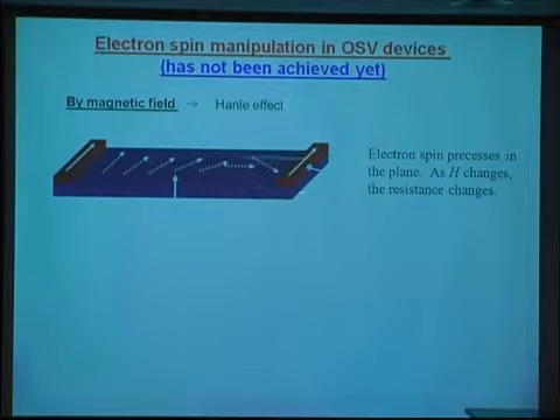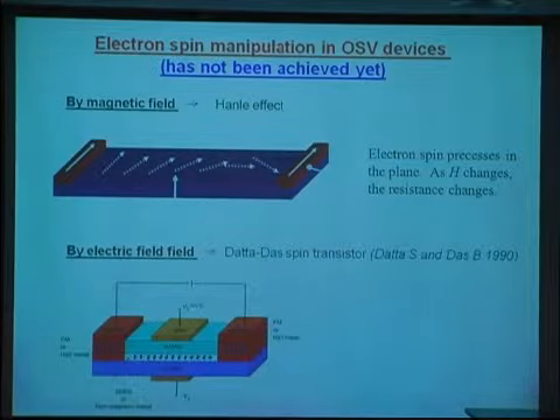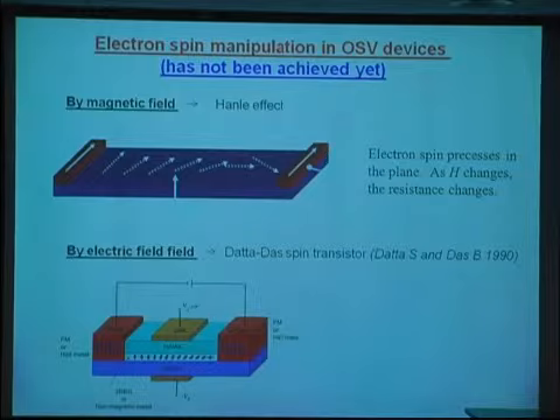And this is well studied. This effect is well done in the inorganic communities. You can see people have done a very nice job, very nice results. But in the organic community, no one has done this yet. And we try to be the first group to report the Hanle effect in the horizontal organic spin valve structure. So the second way that we can manipulate the spin of the electron is using the electric field, and the device was suggested by Datta and Das in 1990.